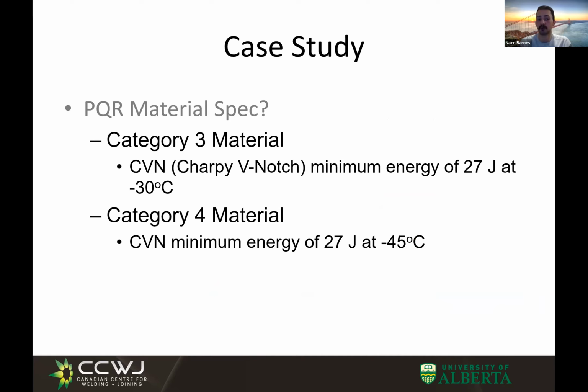But again, to future-proof, and this is a recent change in the code, and thankfully they've listened. It took a long time of talking and convincing people, but essentially it used to be the case that if you tested at category 3, your weld was good for category 3 only. So essentially, if you went up 10 degrees and you were now welding at minus 20, you had a requirement for minus 20, that welding you did at minus 30 was no longer good, which makes no logical sense, because going up 10 degrees is not going to lose you impact energy.